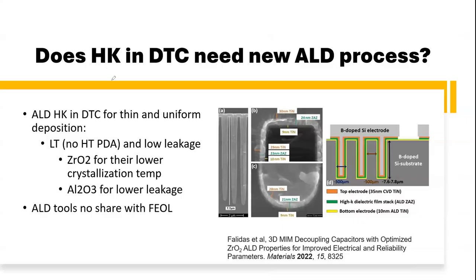And the question is, with high K, why do you choose different materials? You have Z for this ZAZ sandwich layer. This paper is interesting because they use ZAZ as a tri-layer. And they said that zirconium oxide, their Z, is for the lower crystallization temperature. So they don't need high temperature. Aluminum oxide is for lower leakage.